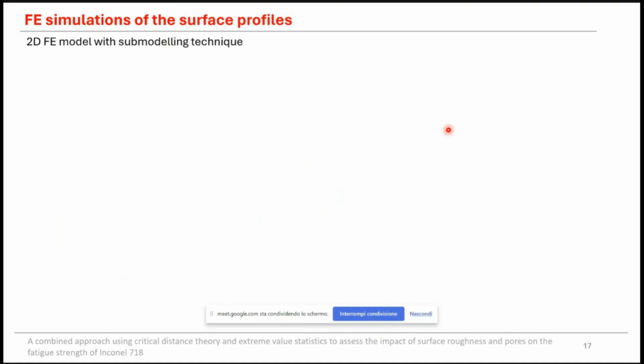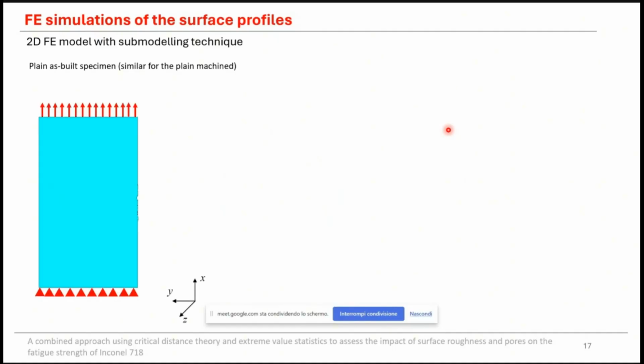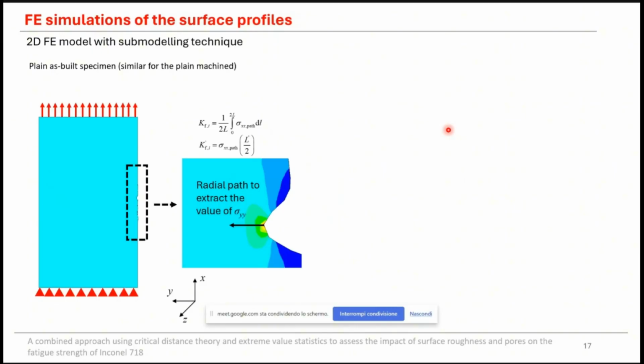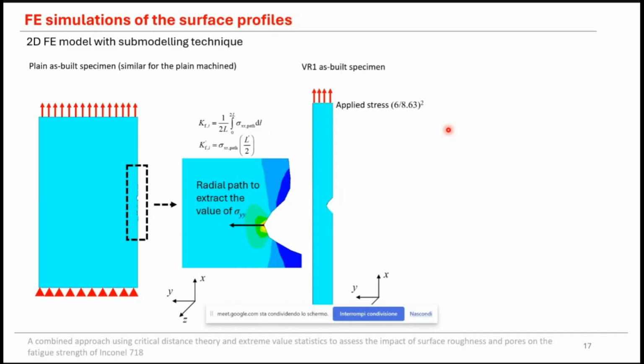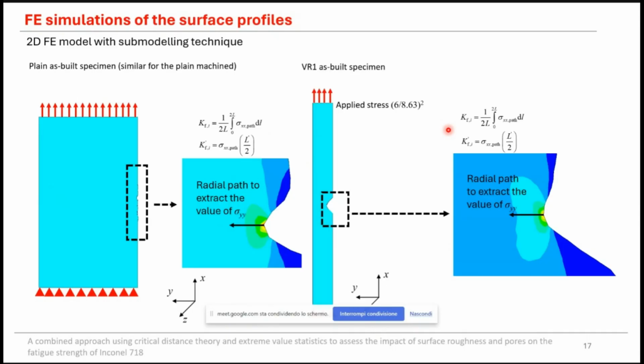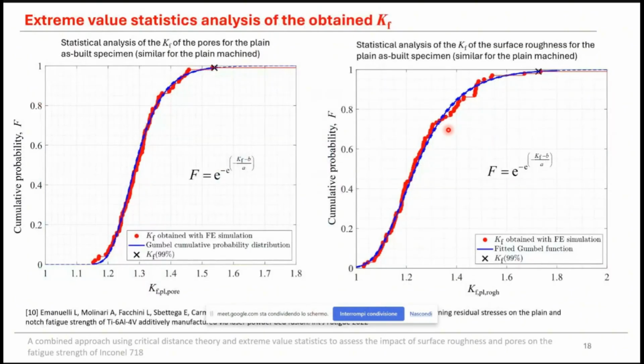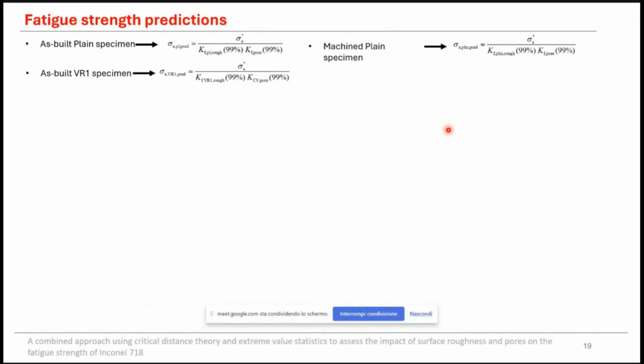We also performed the 2D axisymmetric finite element simulation for the surface profiles obtained through the optical profilometer, with some modeling technique, for plain as-built and machined specimens and for as-built blunt V-notch specimens. And we extracted radial paths starting from nodes experiencing stress concentration. So once the fatigue stress concentrations were obtained, we used Gumbel distribution functions to describe their distributions, and we identified the values at 99% of probability. And then we started performing some predictions.